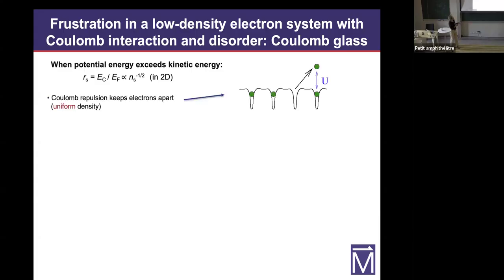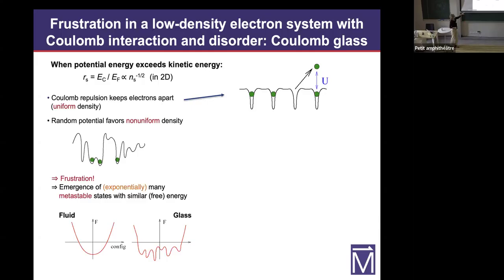If we had only Coulomb interaction, obviously the repulsion would favor a uniform distribution of electrons. But if you have only disorder, this would favor a non-uniform density distribution. So if you have both of these present, what is the system going to do? Obviously, it cannot satisfy both requirements. It gets frustrated. And it was shown numerically decades ago that this gives rise to exponentially many metastable states with similar free energy, and this was termed the Coulomb glass.